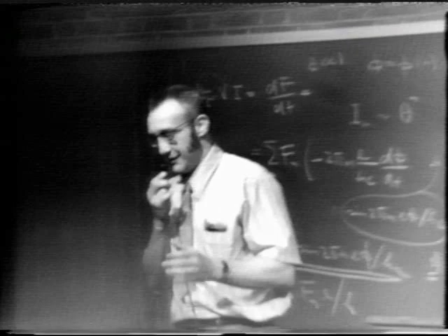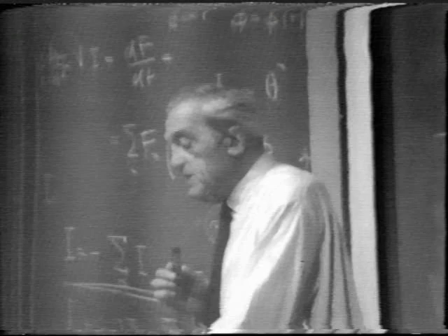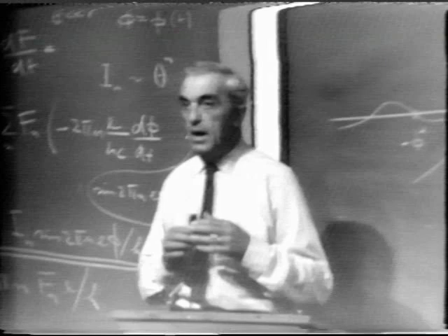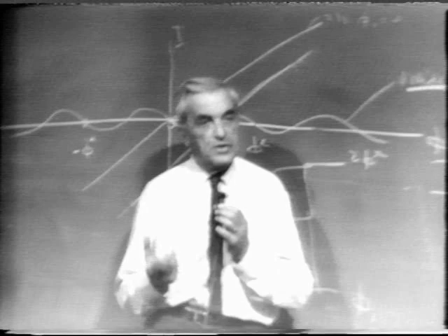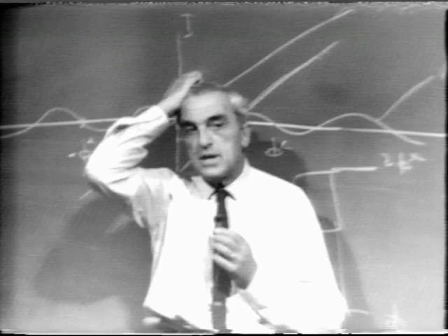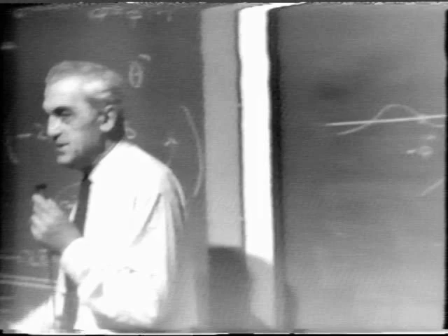Two questions yet. One, what do you think about other interactions other than the electron-phonon interaction? Oh, yes, now that's a very interesting question. It isn't necessarily built into the BCS theory that the pairing process is based upon interaction between phonons and electrons. In order to get pairing, you need an attractive force between electrons which can overcompensate the Coulomb repulsion. And Fröhlich pointed out a long time ago that through interaction with the phonons this is possible, and in fact, that is the basis. When people calculate transition temperatures, that's what they do. They consider the interaction with phonons.